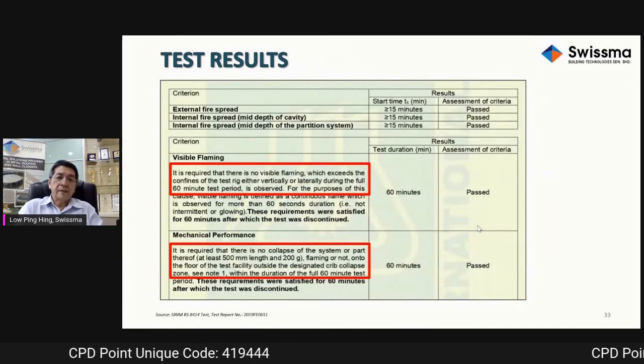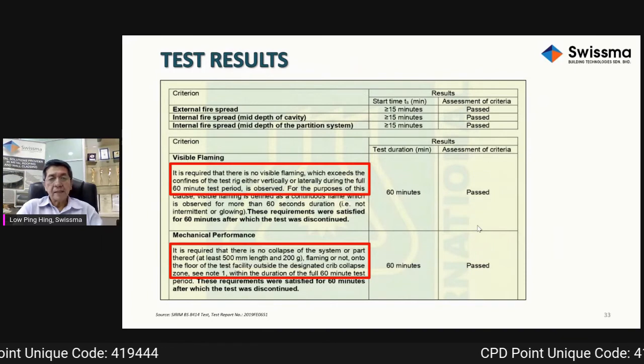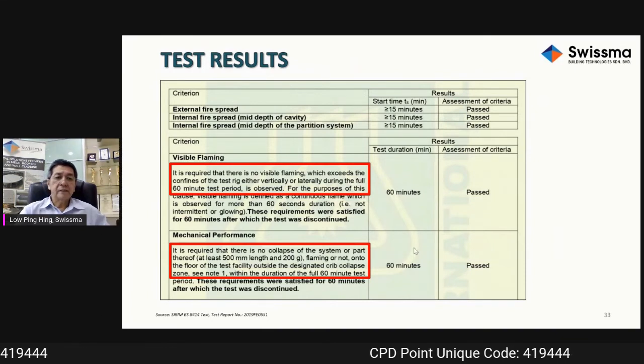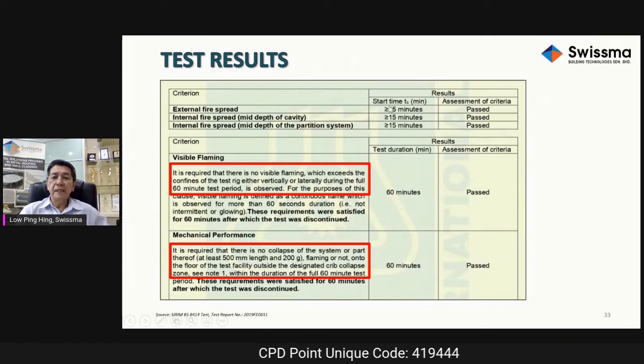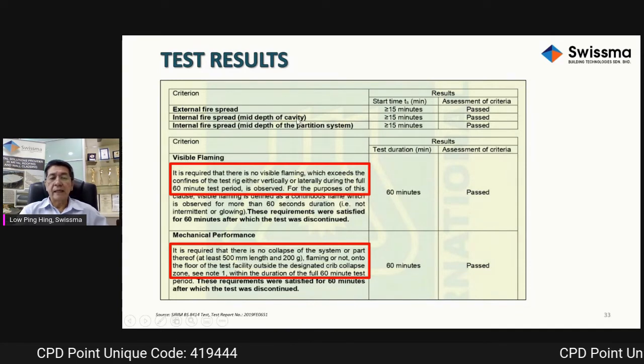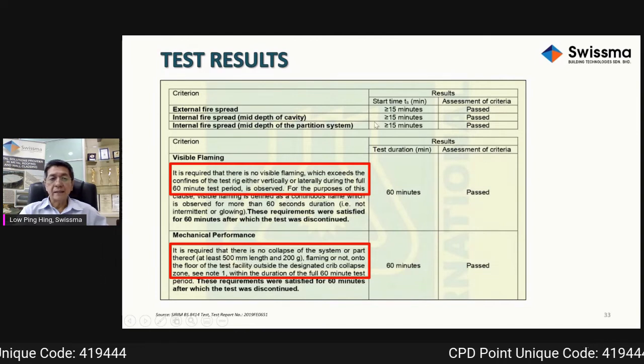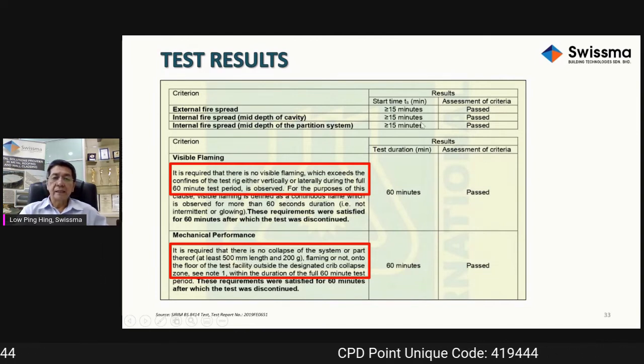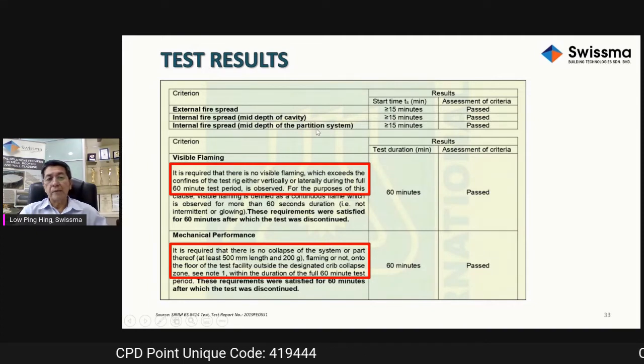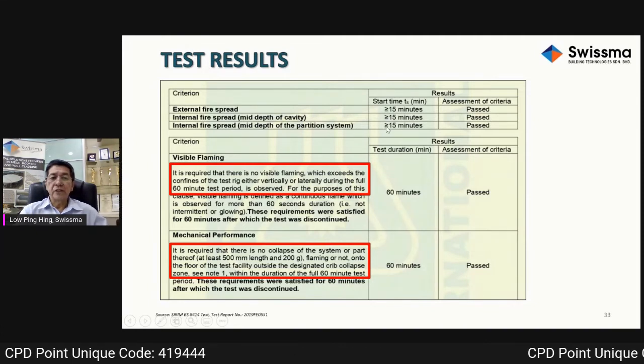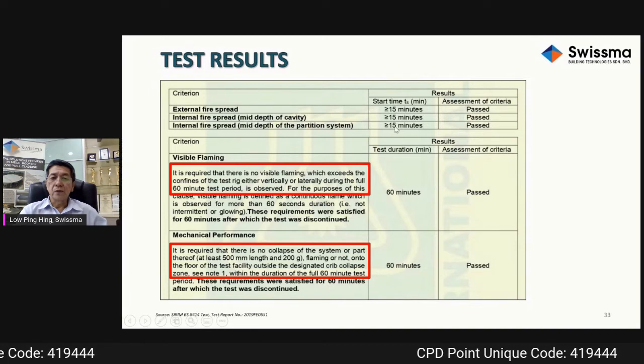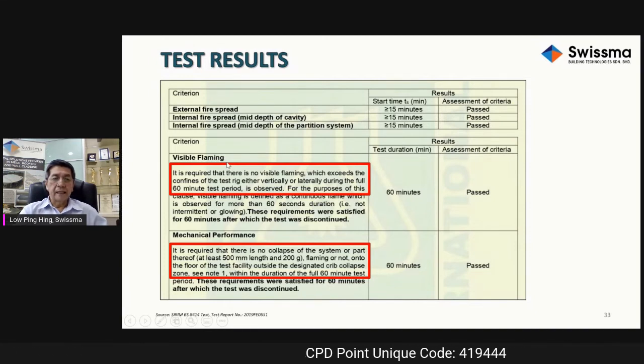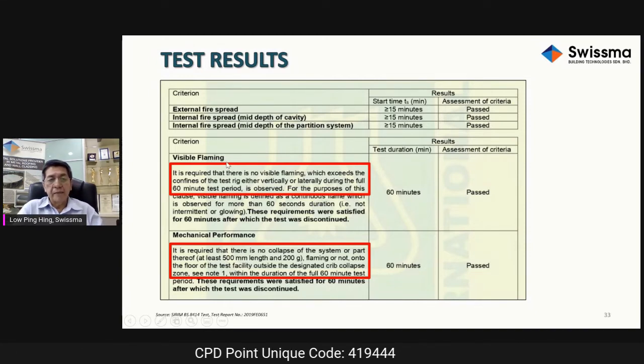So, test results. This is the summary of the test. External fire spread within the 15 minutes or so: pass. Internal fire spread, the cavity area: also pass. All these passes mean less than 600 degrees Celsius. Internal fire spread, mid-depth of the partition. This is an additional measurement for part 2. So also pass.